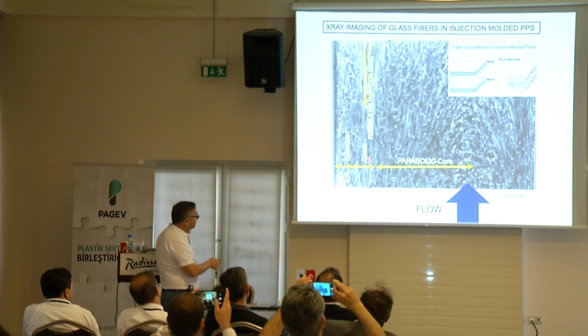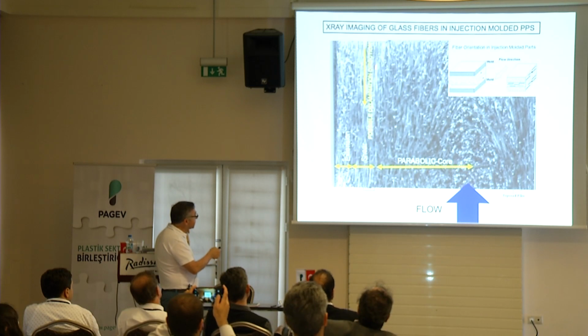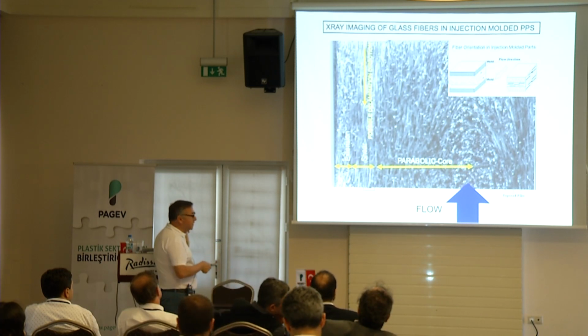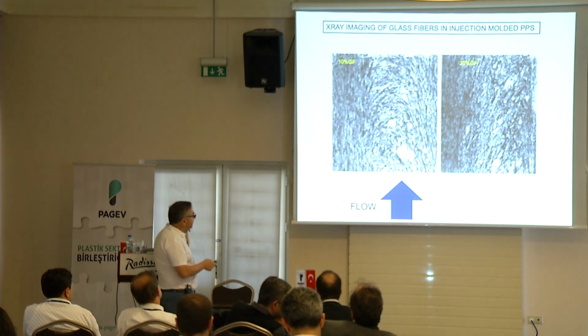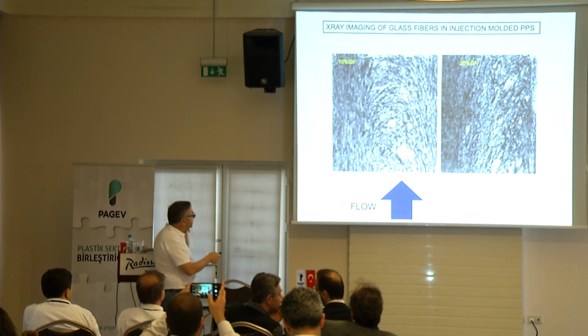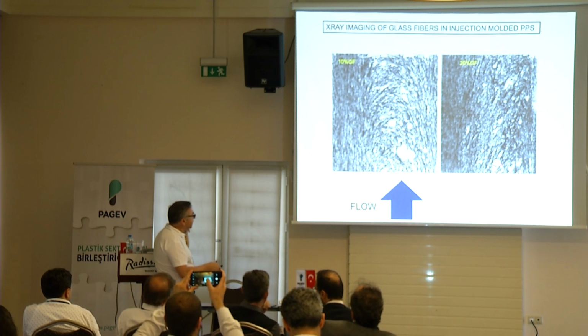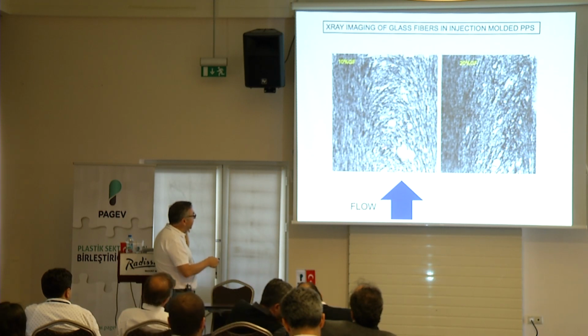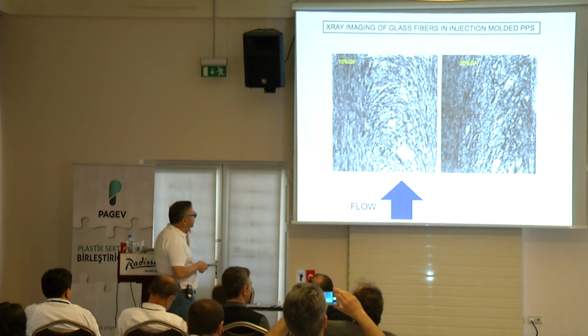Potential delamination, especially in mechanical testing, is a possibility right here on the shear layer, just like what Jakub saw in the PPS. And dramatically in the core, we have seen depletion zones in the material. So the glass fiber can act as a bridge that can lead to this kind of defect in the material.